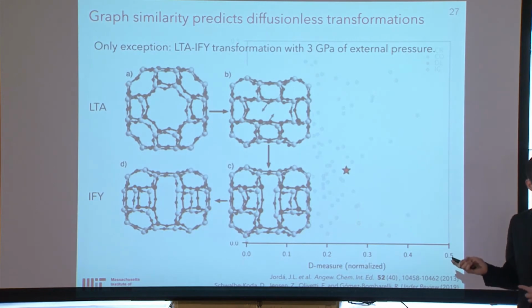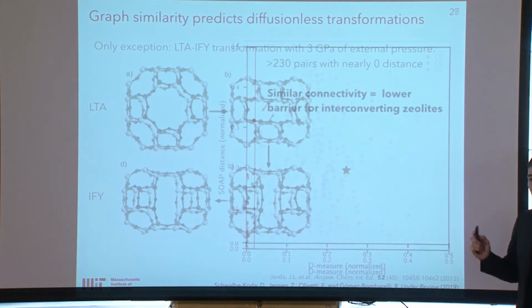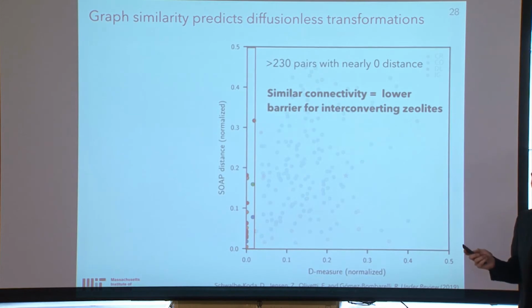It means that the graph similarity metric can fail as long as the conditions to make these transformations are very extreme, such as the application of these 3 gigapascal external stress. So if we look for all pairwise combinations of known zeolites which have very low graph distance, then we find more than 230 pairs that fall on these regions. It means that all of these 230 pairs might contain pairs of zeolites which haven't been observed within such transformations, but in principle could be realized through such processes.